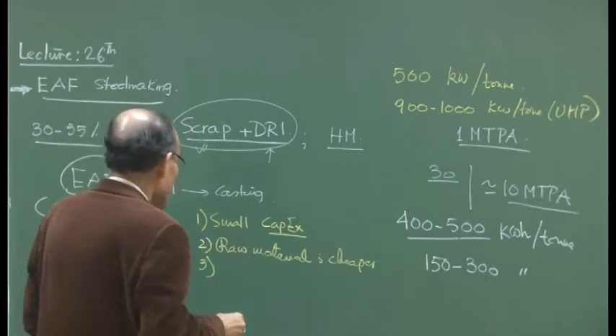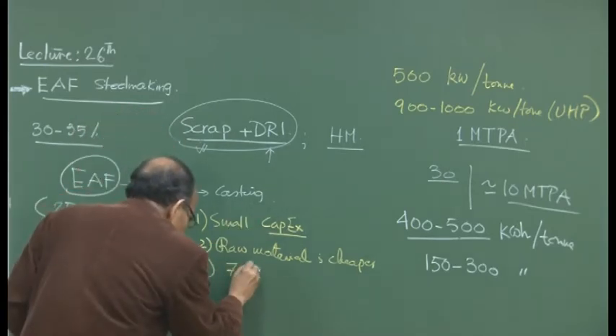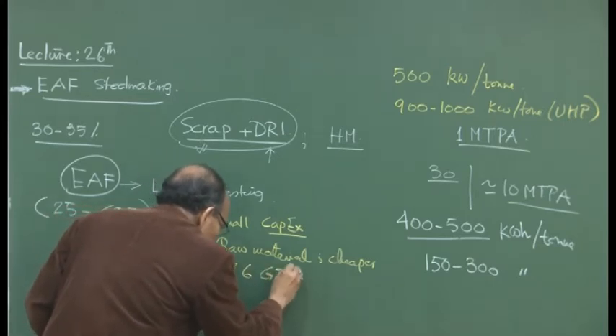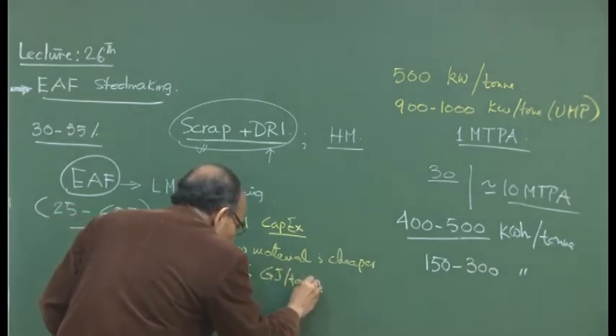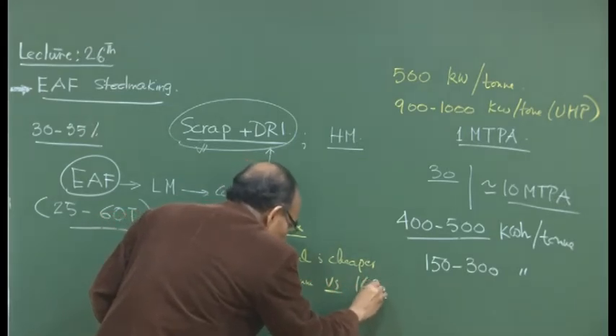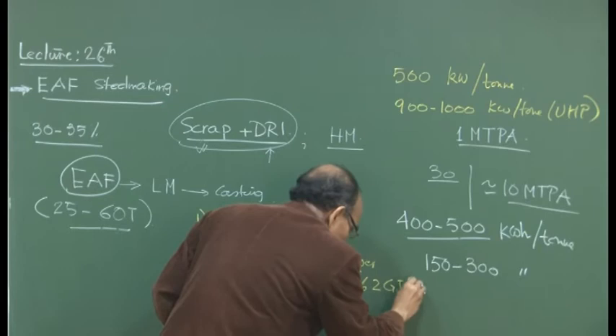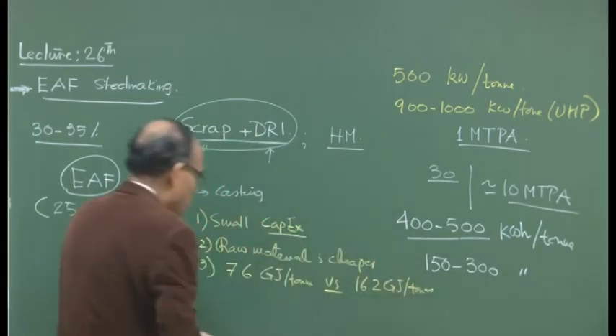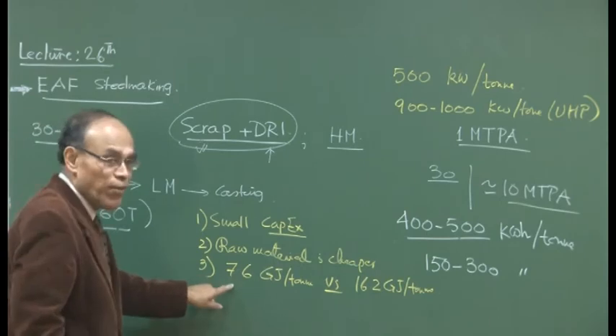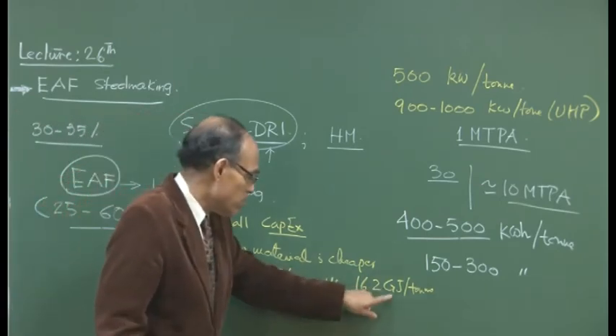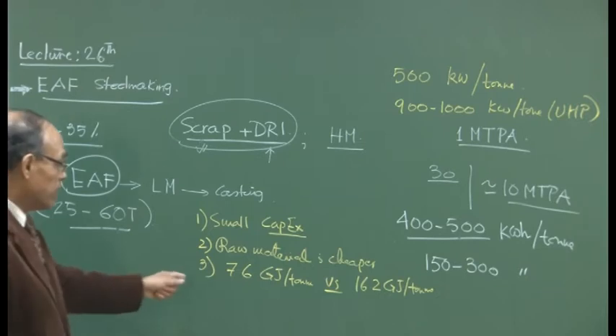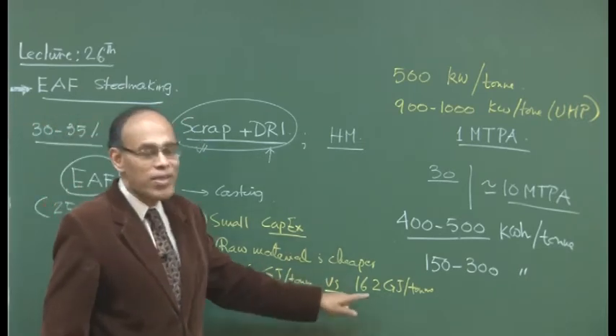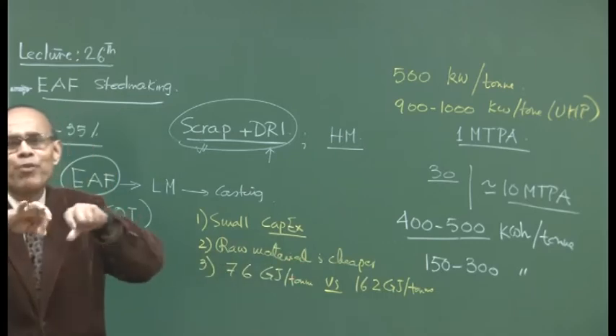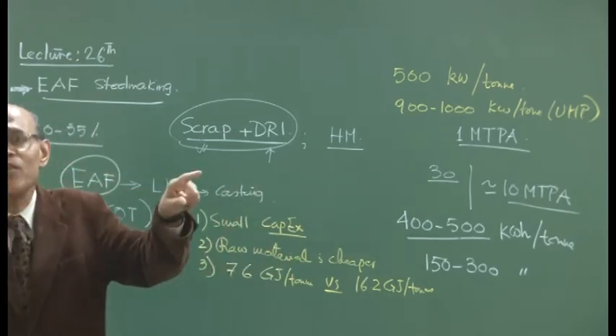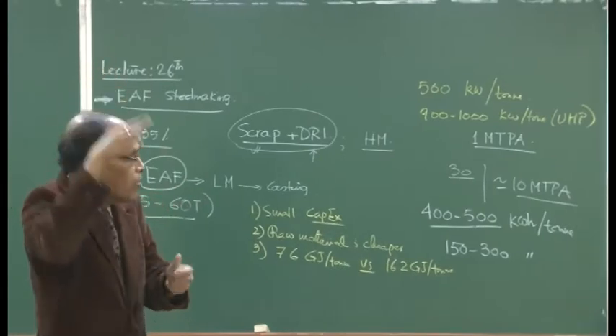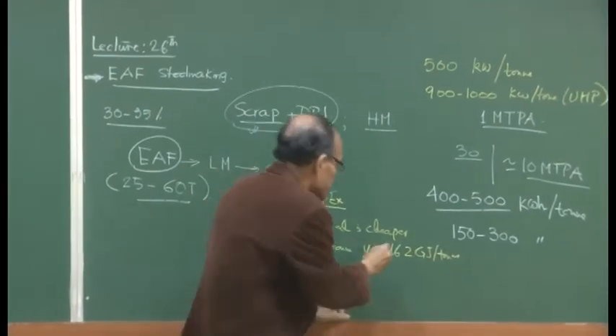And the disadvantageous point is that, in the case of electric arc furnace, you have disadvantages with respect to BOF. So, it has I think 7.6 gigajoules per ton of steel versus 16.2 gigajoules per ton of steel. This is the electric arc furnace, and this is your BOF steel making, an energy intensive process, because in the blast furnace, in the BOF process, you have to break so many bonds, iron oxygen bonds, silicon oxygen bonds. So, the fuel requirement or the energy requirement is 16.2.